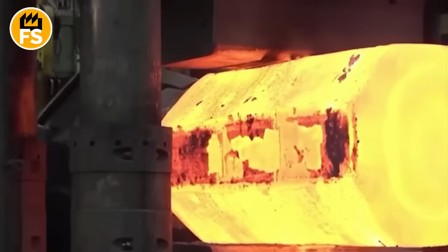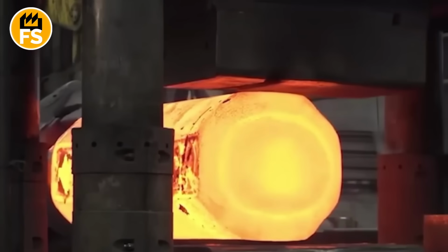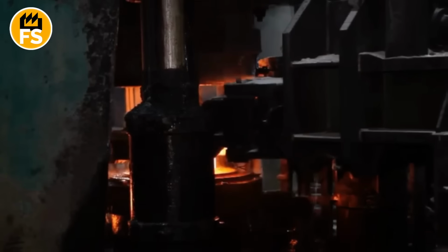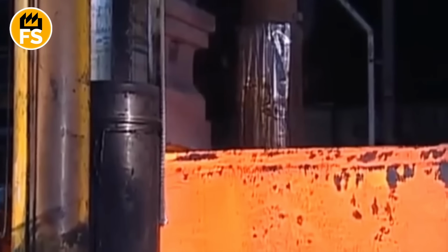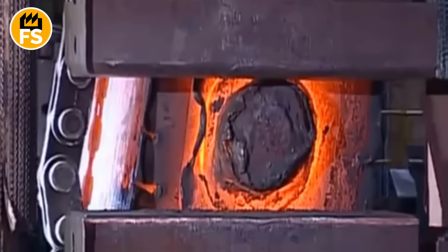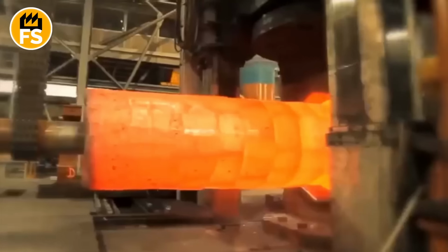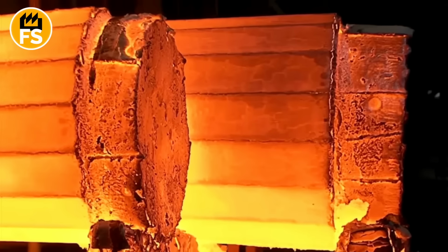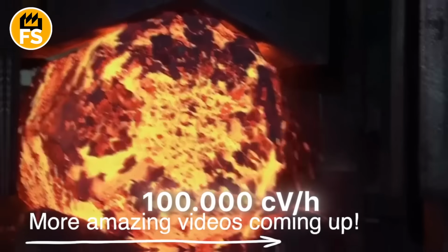The forging process for such an ingot takes several months. It's a constant cycle of heating, pressing, rotating, and reheating. Each press stroke is a precise calculation aimed at achieving the required internal geometry and mechanical properties. The energy needed to maintain the furnace for heat treating ingots during a 2-week cycle can exceed 100,000 kilowatt-hours. That's comparable to the annual electricity consumption of dozens of typical households.